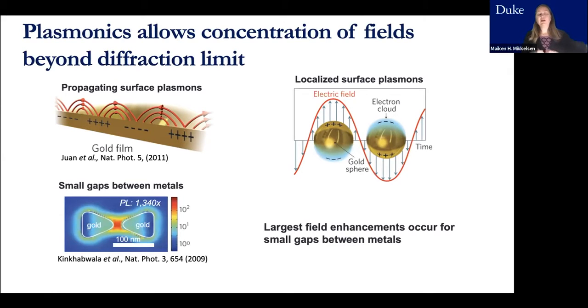It turns out that you can get larger field enhancements if you don't just have a surface or single nanoparticles, but two metal nanoparticles or two metal interfaces close together, such that you have a small gap between metals, as shown in this example with a bow tie antenna and a small air gap here. You can see that red here is indicating a hotspot in this area where there's a large field enhancement. So we can see the largest field enhancements are occurring for small gaps between metals.